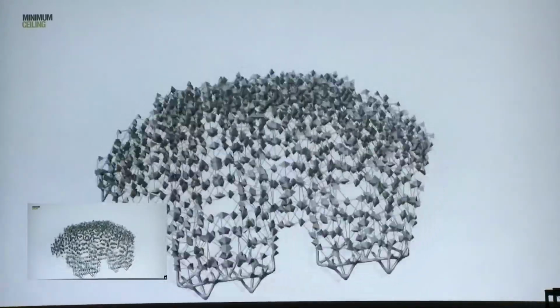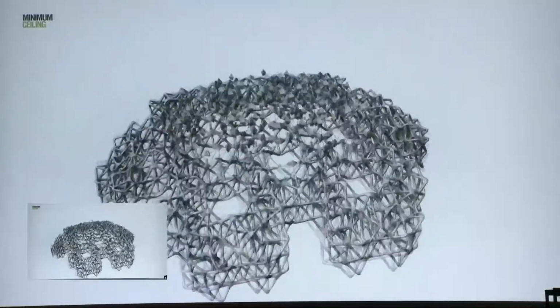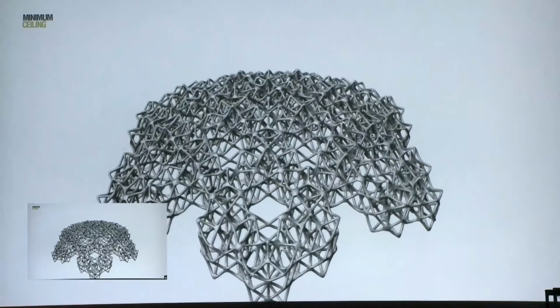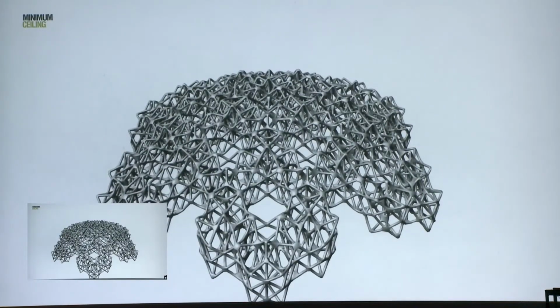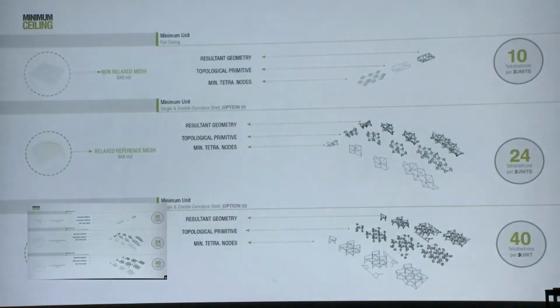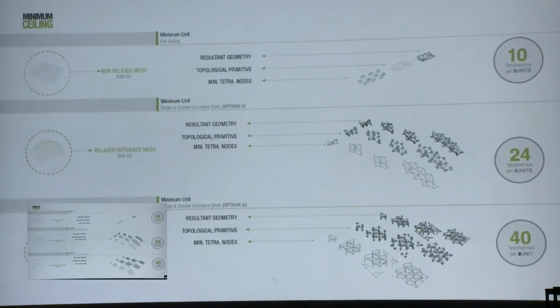First, we started to generate a flat ceiling, but we realized that our structure doesn't really work flat. So we used a mesh and relaxed it, so the triangulation of those elements is within the range of our beams, and then we developed units on top of that relaxed mesh. We developed two units. Those units are only triangulated by themselves. They cannot provide available faces for the next one.